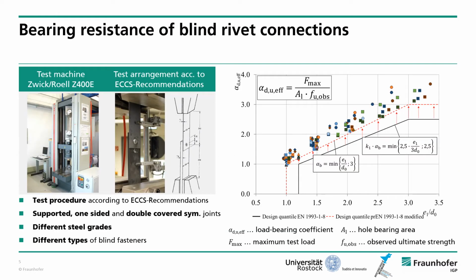For the determination of the bearing resistance of blind rivet connections, we use the test machine Zwick Roell Z400E and the test arrangement according to the ECCS recommendations. Also described in these ECCS recommendations is the test procedure with a specific test speed and also a free measurement length to determine the deformation or the displacement inside the joint during these tests.